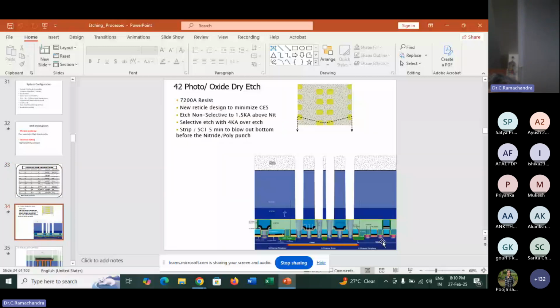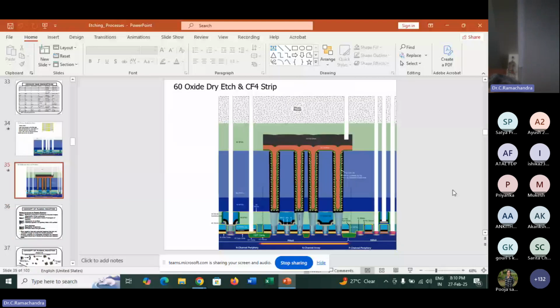As I said, creating this kind of vertical profile is very, very difficult. Though it looks easy, it is very challenging. Sometimes the hole diameter is less than 0.2 micron and the depth is a couple of microns. Now, there are two challenges because we are putting in chemicals which are gaseous. What is the probability that these chemicals enter this deep hole? Otherwise, it will not react at all and remove material. And after reacting, what is the probability that the byproduct comes out and goes out of the chamber? These two things should happen. That is why creating vertical, high aspect ratio holes is quite challenging, and it requires tuning the process parameters very accurately, very precisely.